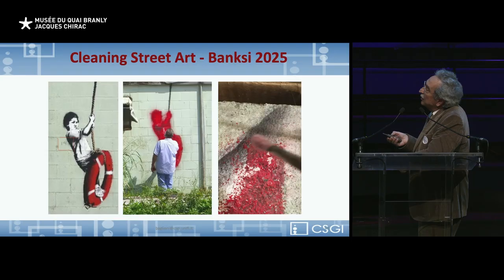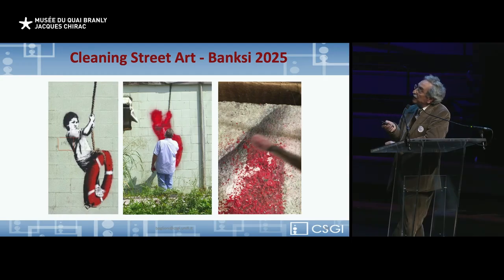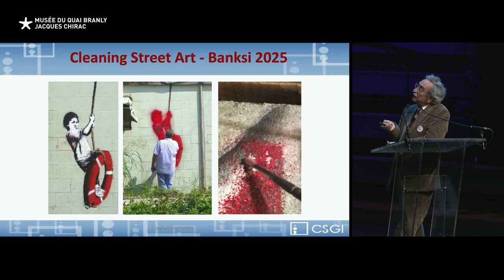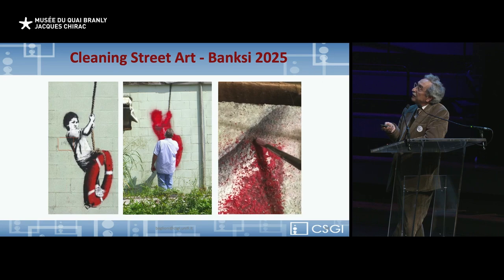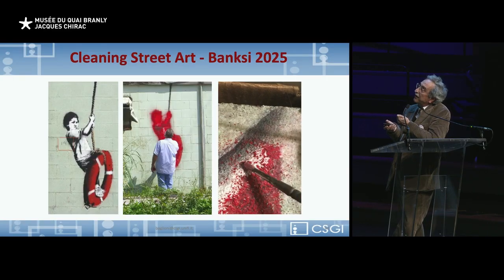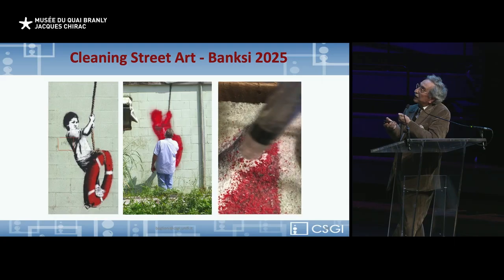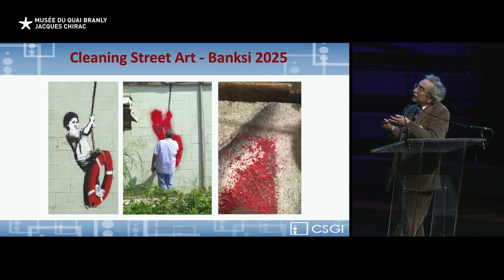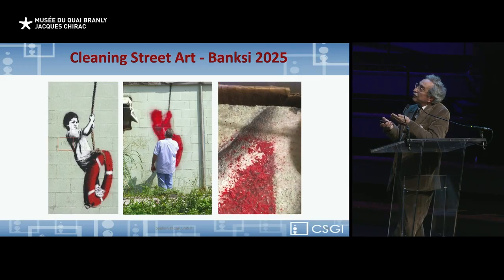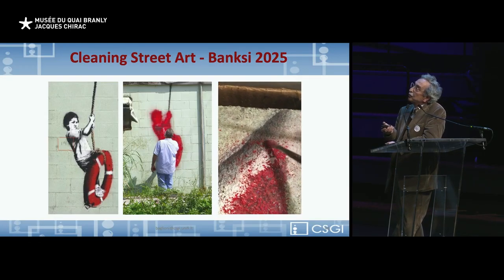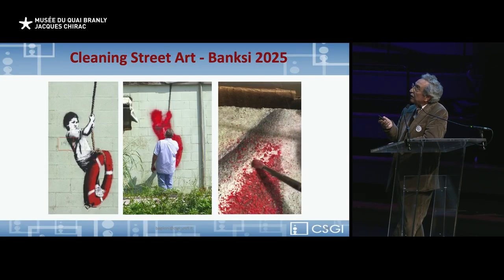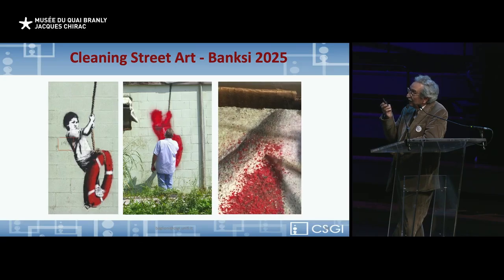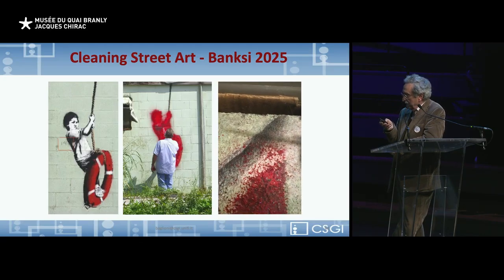So what can you do with this? I can maybe skip this. If you have these gels, you can do something that is difficult to do in a conventional way, for example this one. This is acrylic over acrylic, a Banksy. It was completely difficult. It's almost impossible to remove the red from the original, because if you try to remove the red, you also remove the original, which has exactly the same composition. So if you use conventional solution chemistry, it's almost impossible to remove the red over the white in this case. This is just an example of what you can do with this new methodology.